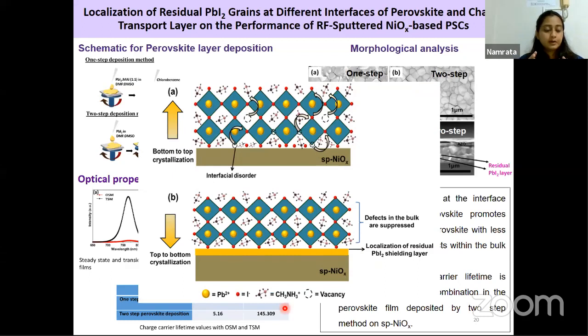And from looking at these results, we proposed a mechanism that when we have a two-step deposited perovskite, we do not have a direct contact of the perovskite with the underlayer, that is the sputtered nickel oxide. That means as soon as we put another layer on top of the nickel oxide, and the perovskite starts crystallizing on top of that layer,